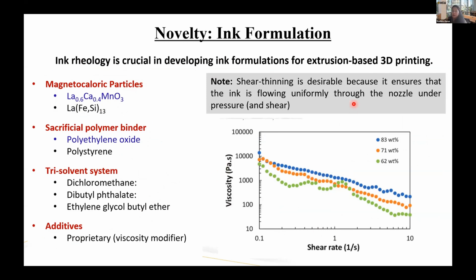The first thing we noticed is that shear thinning is desirable because we want the ink to flow uniformly through the nozzle. 83 weight percent and up works really well for the ink to flow. We can go to higher loadings of magnetocaloric materials, particles, but that has a tendency of clogging the nozzle, so that's also something we're working towards. This is something we can optimize.